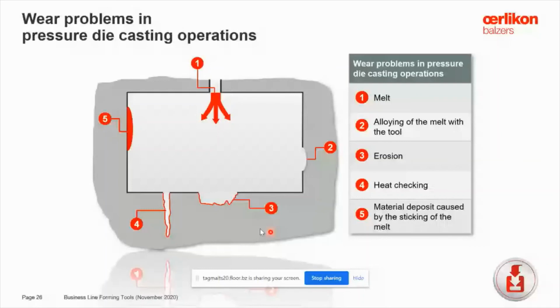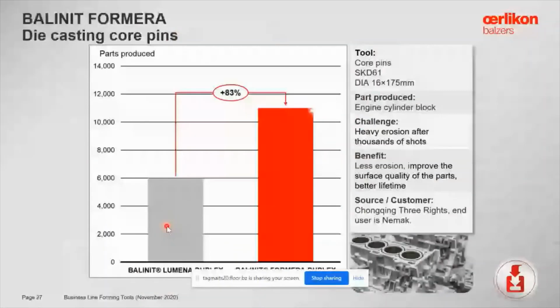Some case studies here for the core pins. The material is of course hot die steel SKD 61. For the engine cylinder block, the main challenge was heavy erosion after thousands of shots, 6,000 shots. And after coating, we could see almost 11,000 shots, or 83% life improvement. This is a customer which is also global, which is Nemak.